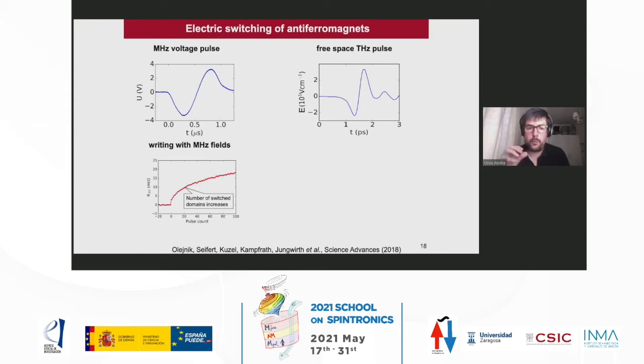So what they observe by looking, after applying this terahertz pulse, or a number of terahertz pulses, is the magnetoresistance, or the dynamics, or how the magnetoresistance changed with each pulse. What they observe is that the pattern is the same, or very similar to what they observed with megahertz voltage pulses. So this is a signature that just with a terahertz pulse, you can induce magnetization switching.